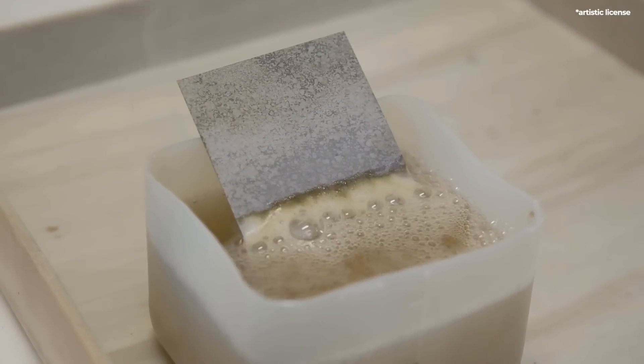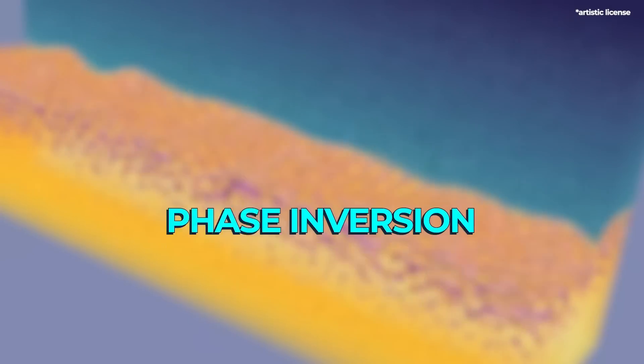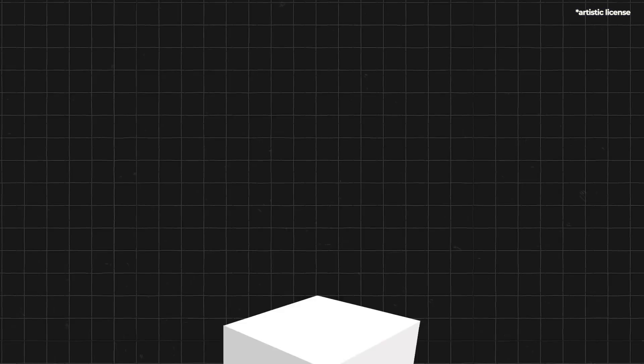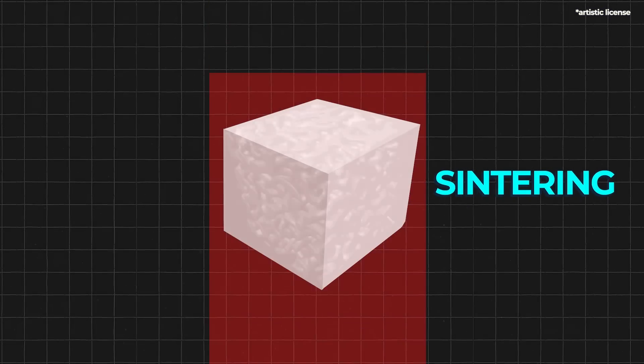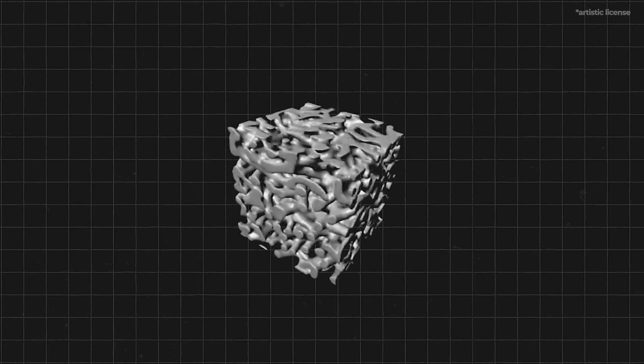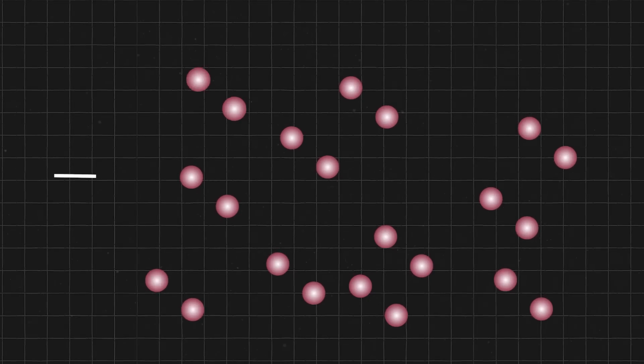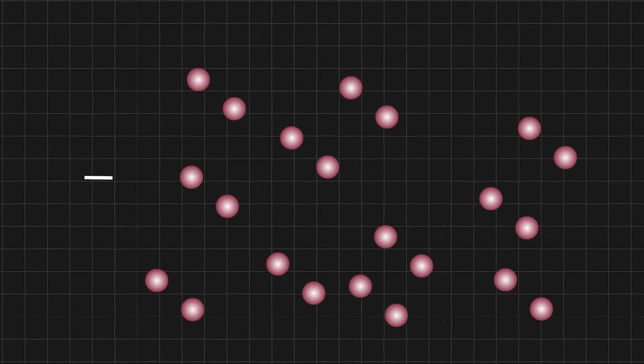The material is produced by after casting it on a flat substrate, the material was immersed in an ethanol bath. The material then unmixes itself in a process called phase inversion, which takes place as the ethanol diffuses into the casting and dissolves any NMP that it comes in contact with. Following sintering to remove any PES, this process forms a random porous network carrying alumina particles throughout, producing a structure that looks very similar to the Cyphochilus beetle's scales. And although this manufacturing process might sound complicated, this is pretty easy in terms of fabrication in the grand scheme of things. It doesn't require either precision instrumentation or fine control of the parameters. What researchers did find is that by manipulating the alumina concentration in the phase inversion precursor, the team was able to produce a very short transport mean free path, meaning that photons are highly efficiently scattered.